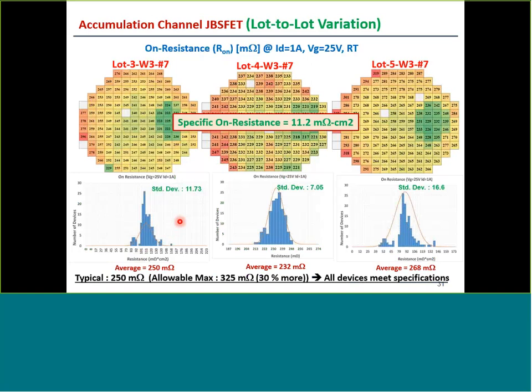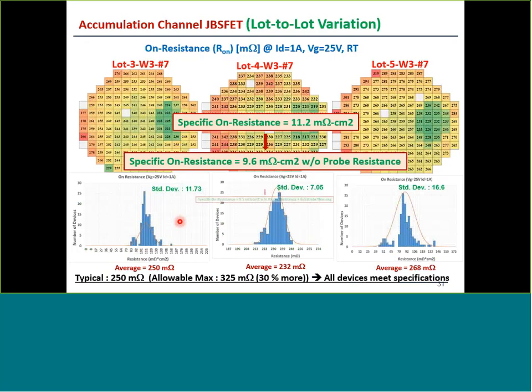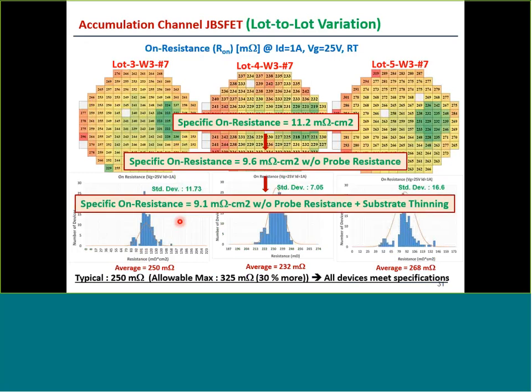The specific resistance for this design works out to be 11.2 milliohm centimeters squared. Again, that is actually translated to 9.6 milliohm centimeters squared if I remove the probe resistance, and if we were to thin the substrate, this would come down to about 9.1.